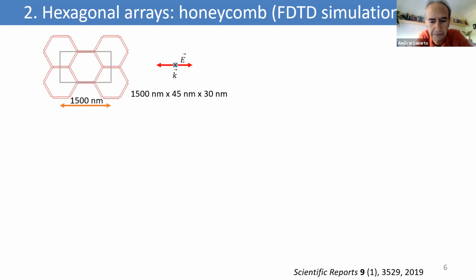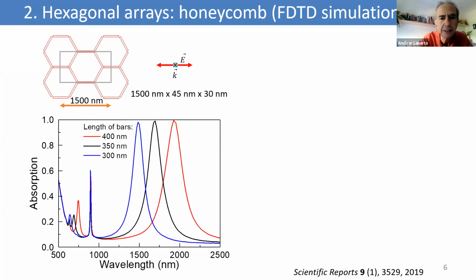And the idea is if this near-field excitation is not really fulfilled in the lattice, this energy could be transferred to another mode, which could be these collective modes, okay? So if we look at the absorption, this is the absorption for this lattice. Here you can see 3 curves. Each one corresponds to a different length of the bar, but keeping constant the pitch. So the 2 peaks that are changing with the length of the bars are those related to the near-field interactions. And the one which isn't changed when we are varying the length of the bars is the one which depends only on the pitch. So it's the one related with the collective excitation. Let's say something like a Bragg reflection of the lattice, okay?